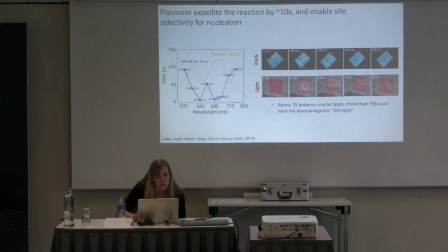And I don't think I included it here, but basically the diffusion time remained constant, which is kind of what you would expect. Basically, for diffusion to occur within the nanoparticle, it doesn't really matter if light is there or not. And that also was kind of an indicator that there's not so much heating going on, because we're not expanding the lattice and making diffusion faster, because, you know, diffusion is thermally activated.